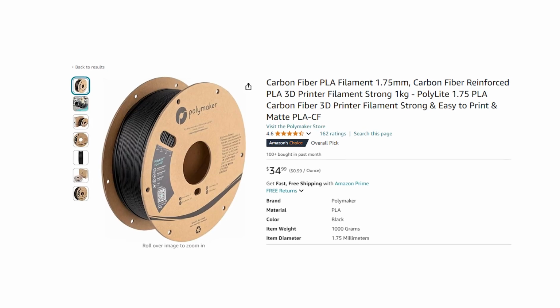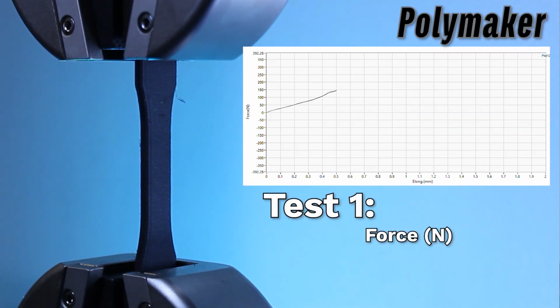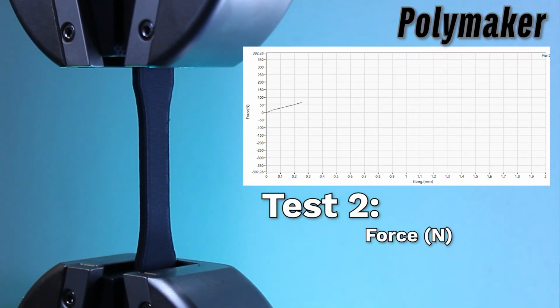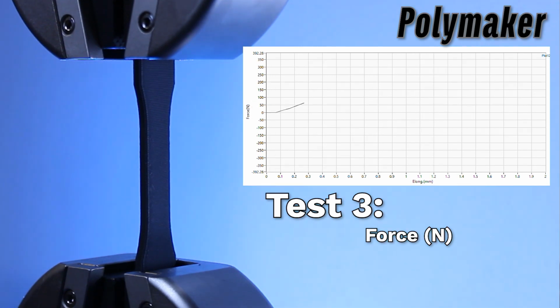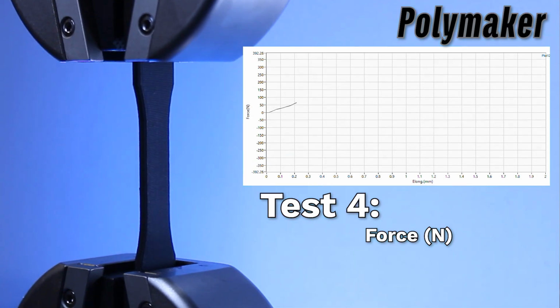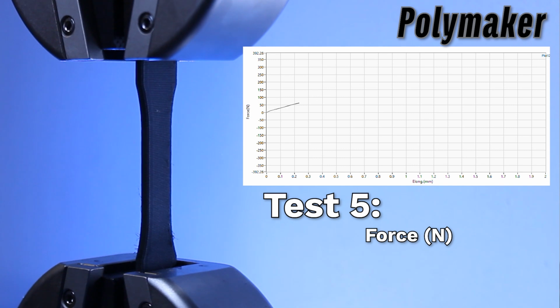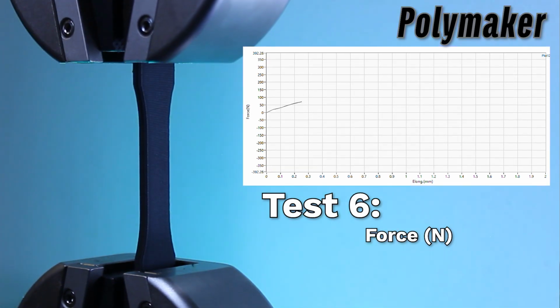We know that standard PLA, standard black PLA run out of our extrusion with no sort of fillers at all except for the colorant, is able to take a maximum force of about 1700 newtons and all the way down to about 1300 newtons depending on the situation, which is a tensile stress of about 33 megapascals. The very first item we tested was Polymaker CF. When we tested it, the average force that it was able to take was 717 newtons, which is a full 1,000 newtons less than standard PLA.